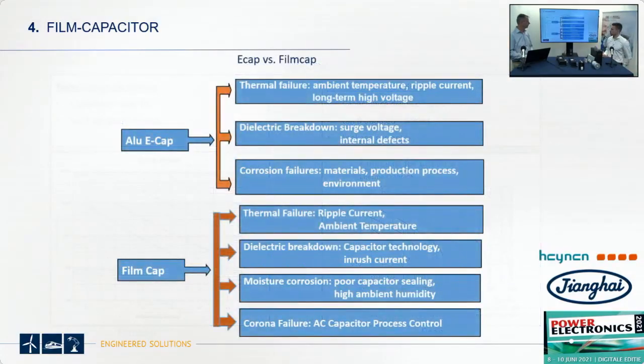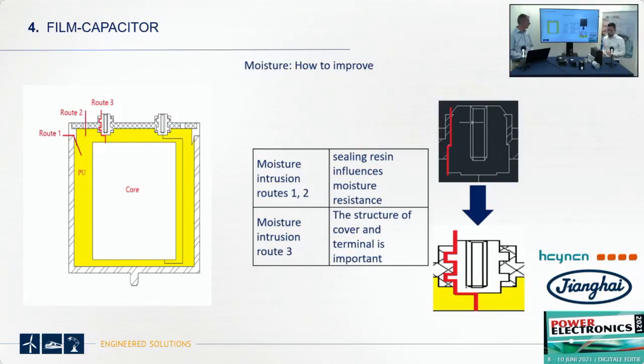So the failure modes are quite similar. You have the thermal failures from the ambient or during the current increase of the temperature. You have the electric breakdowns, but the difference in failure modes for film capacitors is the moisture corrosion. This is not so important for ECAPs, but for film caps. And therefore, we have several changes inside of our capacitors. We use different filling materials for the aluminum cans. We use PU, different PU fillings for the modules, and for the small DC links we use epoxy.